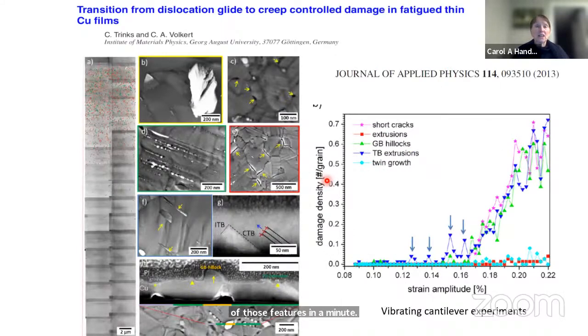Now, I took a lot of inspiration in this paper by Trinks and Volkert. I had been working on this area for quite a long time, but they have done what I think is the definitive work in trying to break down what the different kinds of deformation mechanisms are operating. What they did was they have a thin film, as a function of the strain amplitude. They put a thin film on a cantilever, and they vibrate the cantilever, and there is a strain gradient along the length of the cantilever. It's a vibrating cantilever, and this is where the stresses are highest here and the lowest here.